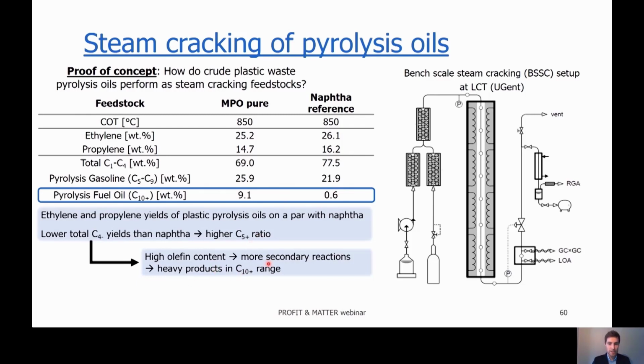And this is mainly due to secondary reactions, which are basically due to our high olefin content in the feedstock. And that means that these feeds need pretreatment. It's not feasible to use these feedstocks pure in a steam cracker because we have a lot of fouling and coking issues expected. So in order to reduce these tendencies, we need to pretreat these feedstocks.